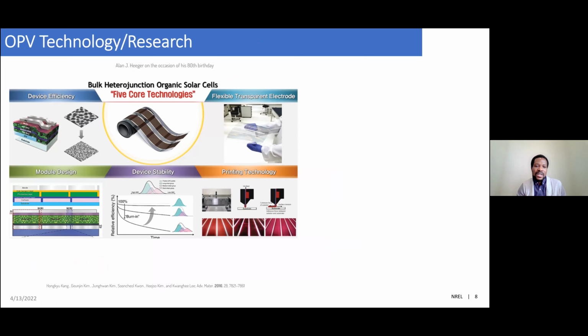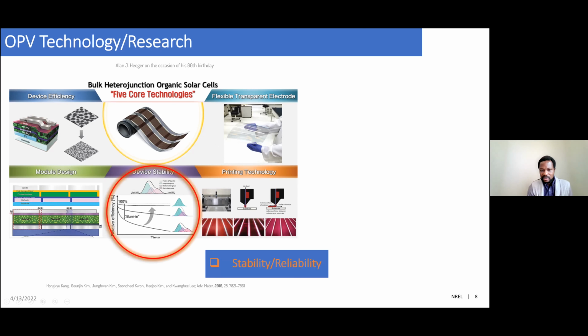And as a summary, I like this graph a lot, which is from a publication done in honor of Alan Heeger, one of the forerunners of the bulk heterojunction technology. Here we can see that they have identified 5 core issues that will have to be addressed to push this technology further: efficiency, which we have already tackled, and module design. Also, we have to look at flexible transparent electrodes, especially when we want to do printing on flexible substrates. And most especially device stability, which is about reliability, or durability, depending on whichever way you look at it.